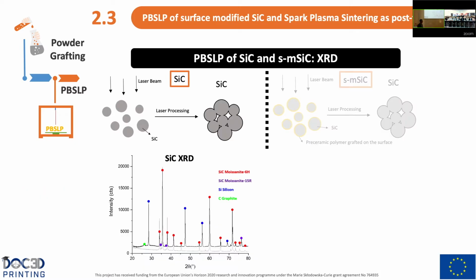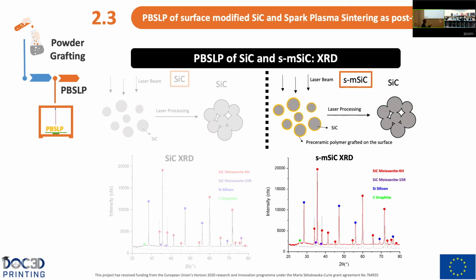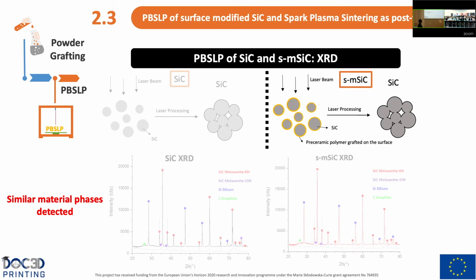Here we have the phases of the material, the XRD spectrum. For the silicon carbide, again, as we have seen, two phases like the powder as received, and two due to the composition. Regarding the surface modified, again, two like the powder as received, and two phases due to the composition. So actually here we have similar material phases in both cases.